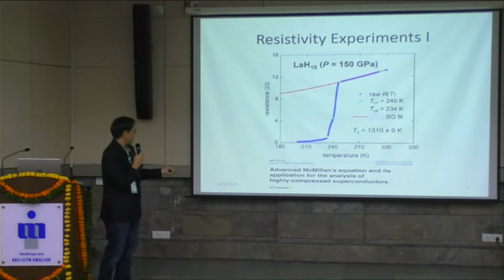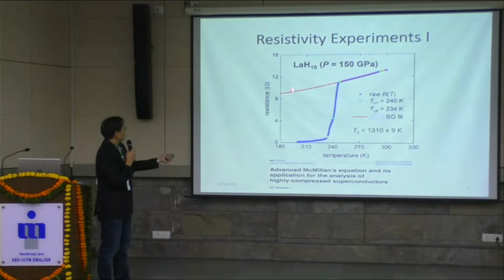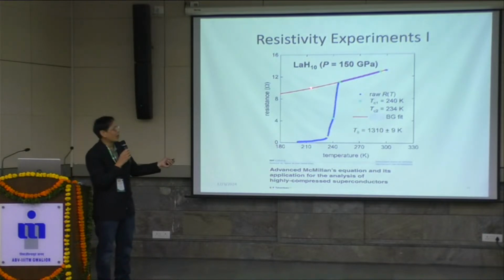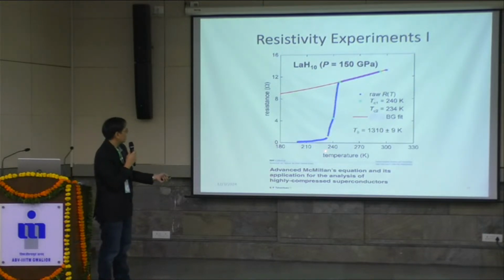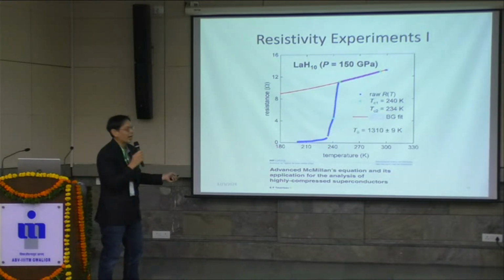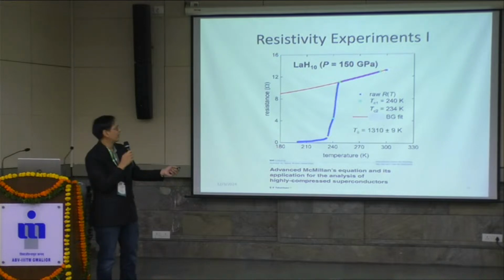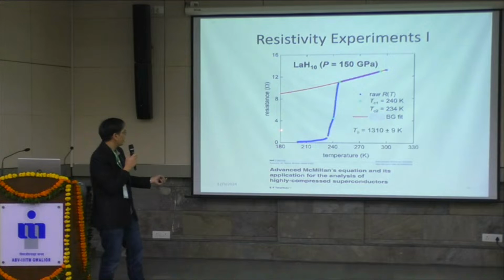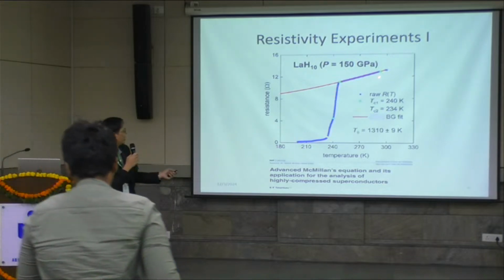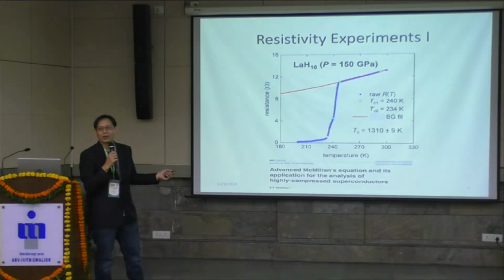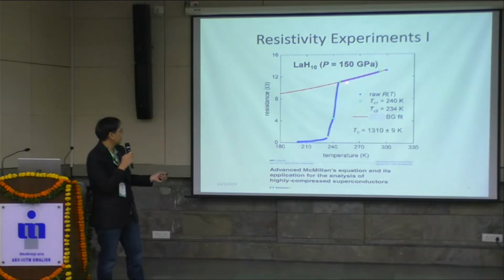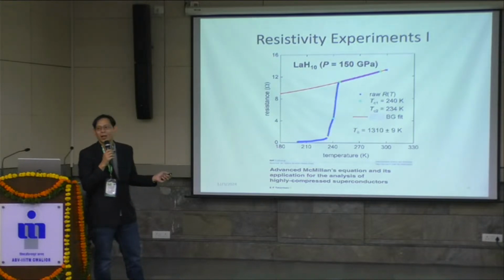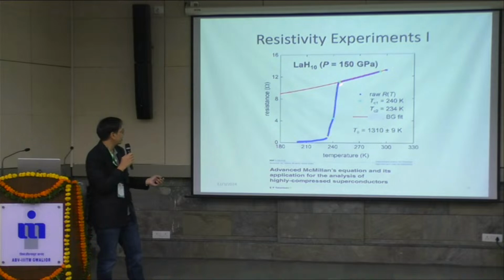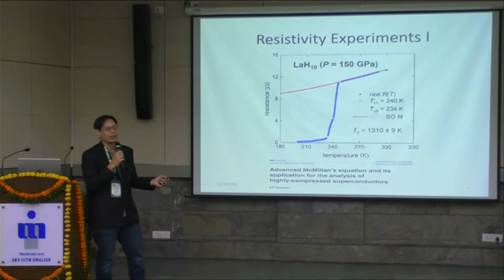Someone measured the resistivity of lanthanum decahydride, and at 240 Kelvin, after that, it becomes a superconductor. Right? You can see it becomes a superconductor in this area, in this temperature. But if you raise the temperature a little bit, it becomes just a normal conductor, and its resistivity increases with the temperature, like this.